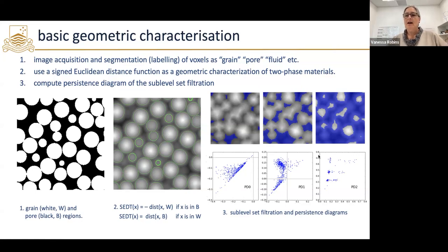The degree 1 persistence diagram is then characterizing the number of redundant pathways through the pore space, basically. And we have some births and deaths within the pore space itself. So this means there's a very highly non-convex pore in the pore space where I generate a cycle within the pore space before that gets filled in. So I've got an index 2 saddle point in the distance function sitting in the pore space here. That's what that says.